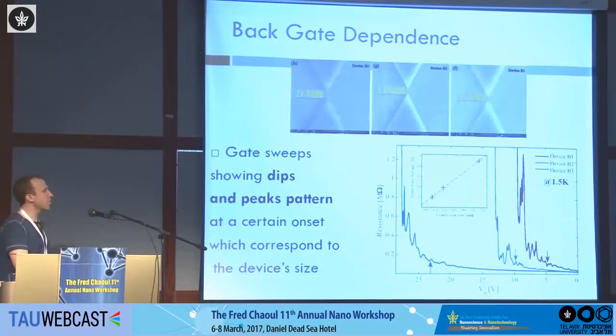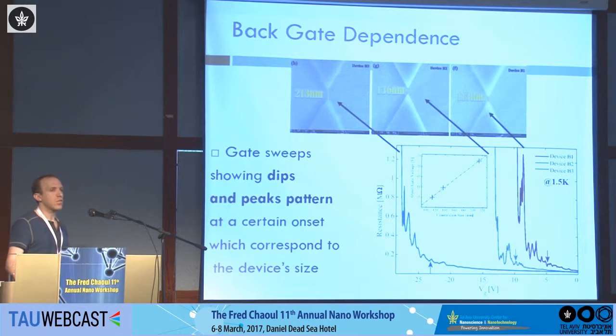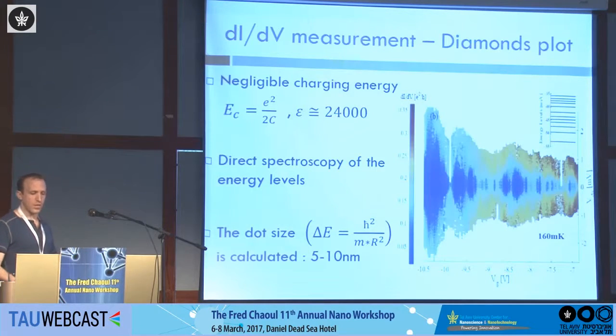Here we see, at a certain onset that actually corresponds to the size of this constriction, a pattern of dips and peaks, which actually resembles some kind of tunneling effect. And when we got this, we thought we were having something really interesting. So we went and wanted to do the main measurement you do when you think you have something like a quantum dot. You measure the dI/dV measurement and try to see a diamond plot. And this is what we did.